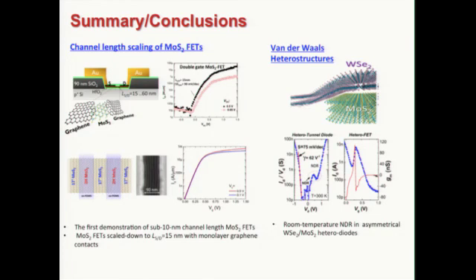Yeah. And yours, the interface with the moly disulfide is sort of unusually clean, or at least you know what you're doing when you put it together. With the tungsten selenide, you mean? You mean in the heterostructure? Yeah, because then you get this very steep 75 millivolt. Yeah, well, we work on the transferring technique, to make sure that the interface is very clean, and normally you have air bubbles between. So we need to somehow iron it to remove those bubbles, because if we have bubbles trapped between, that also is an extra barrier.